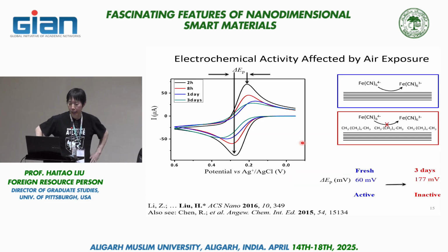So we take a look, and we realize that we just need to do a cyclic voltammogram. If you recall the tutorial yesterday, what you do here is you scan the voltage and you collect the current. What we did here is we have a piece of graphite and we exfoliate the top layer, so now we have a clean surface of graphite. We use this clean surface as the electrode to collect cyclic voltammograms, and we do this as a function of time, the amount of time we left the electrode in air. This is done using the ferrocyanide redox couple, which is a one-electron redox couple.